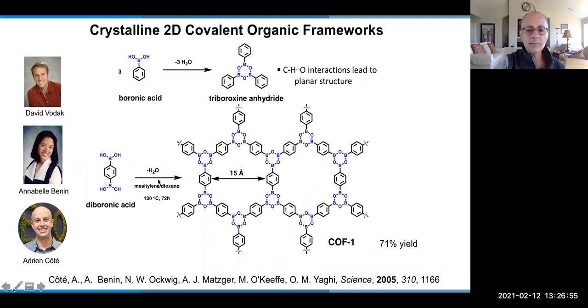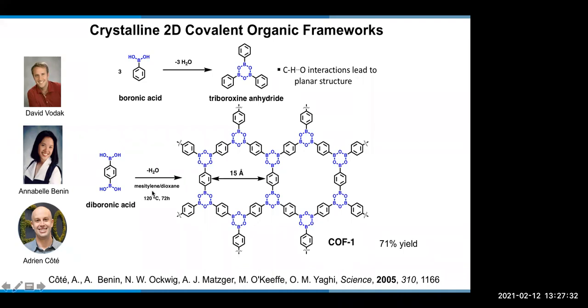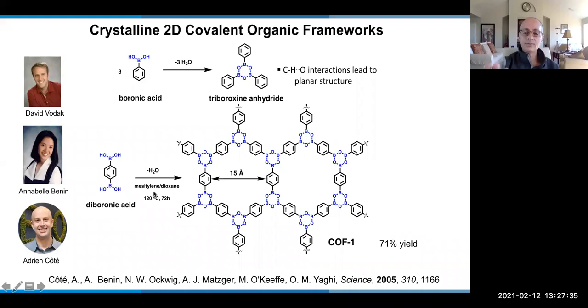Let me describe what I mean by that. If you look at this reaction, it produces water. When you're running this reaction, let's say at the time we were running these in a closed vessel, water is produced and it sits above the liquid. And so we realized that by controlling the amount of water above the liquid, or let's say controlling the pressure of water in the vessel, you could also control the reversibility of this reaction. And if you have the right solvent conditions to balance also the solubility of water in that solvent, you're able to find the perfect conditions to crystallize this material.